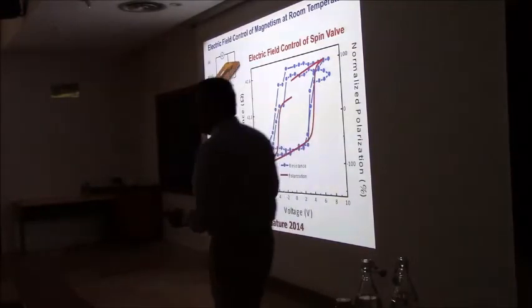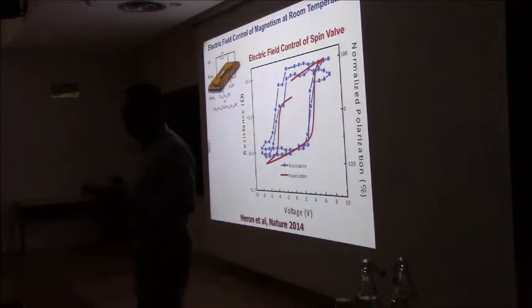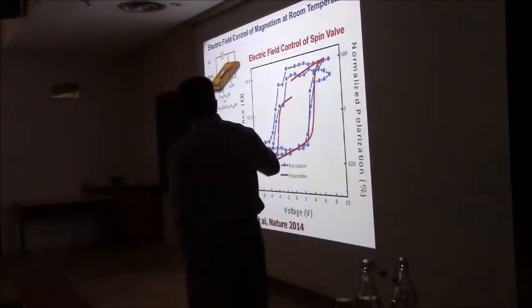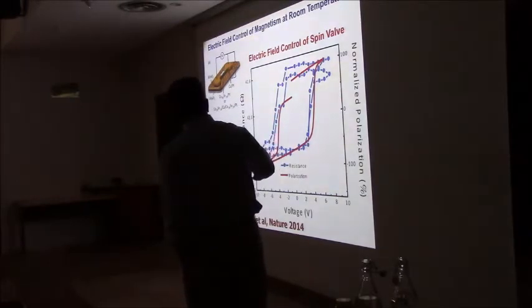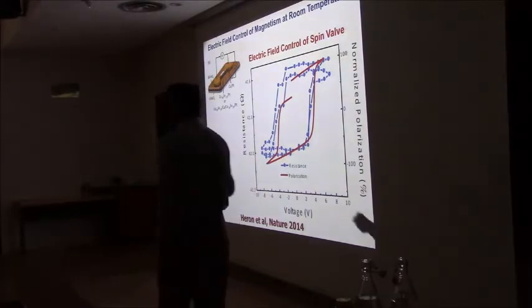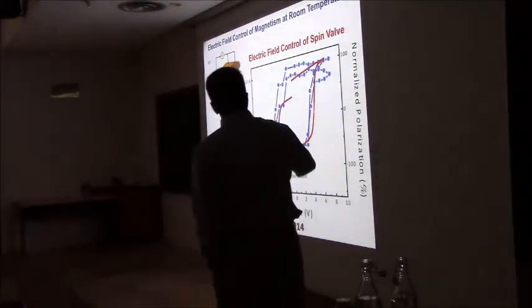We built a spin valve and said, can I manipulate the transport through the spin valve? This is a current in-plane spin valve, by applying an electric field. And what he showed was, indeed, you can do this. You can get the hysteresis loop, which is about 1.5% or so change in the resistance, which is approximately what you expect. So it was all good. The fact that it's coinciding with the ferroelectric switching was very interesting.